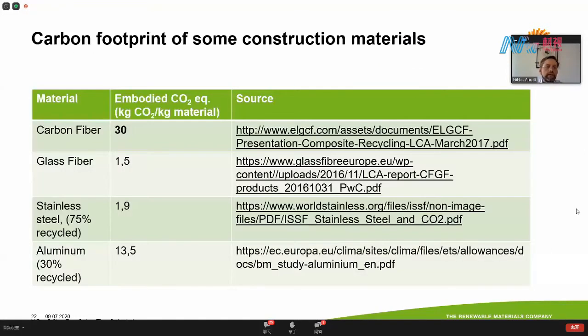But there's a problem, and that's the carbon footprint of carbon fiber. In this table, you can see the carbon footprint of carbon fiber compared to other construction materials, and you can see that the carbon fiber has a footprint of about 30, meaning that for the production of 1 kilo of carbon fiber, about 30 kilos of carbon dioxide equivalents are being emitted. And this is much, much higher than the CO2 footprint of other materials. Glass fiber at 1.5, stainless steel about 2, depending on the recycling rate. Aluminum about 15.